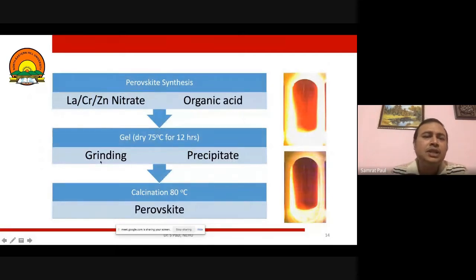Now, how can we synthesize perovskite? Suppose for A and B, we can take lanthanum, chromium, zinc, or titanium, anything. Normally, whatever perovskite we need to make, we take the nitrate of that particular salt, and on the other hand, we take one organic acid. If we take an organic acid, we'll have a mixed type of perovskite, meaning the perovskite will have an organic component and an inorganic component. So these organic-inorganic combined types of perovskite have different types, as we have already discussed, where organic and inorganic compounds can be combined.